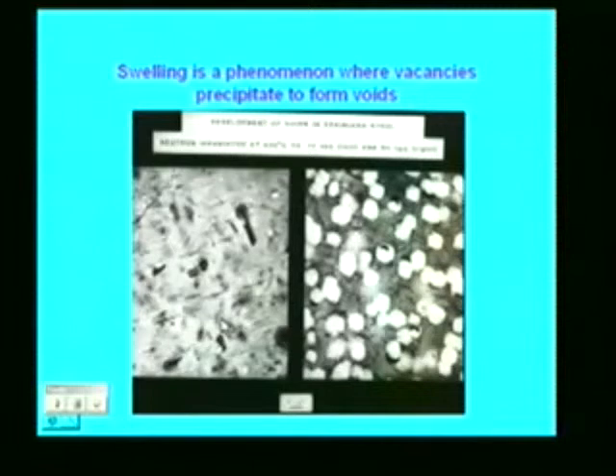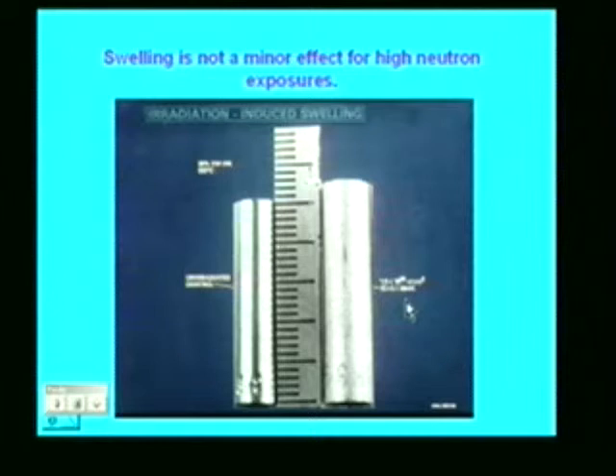And here we have a micrograph showing stainless steel, first irradiated to 10 dpa, and you can see among some other features we have some voids, and then irradiating it to 50 dpa, the material is starting to look like a sponge. So swelling is not a minor problem. And just to put it in perspective, this is a before and after. That's a rod that was irradiated in the Fast Flux Test Facility at Hanford, Washington. Shows the fluence here are 1.5 times 10 to the 23rd, and that corresponds to about 75 dpa. And that's a 30% volume swelling increase.